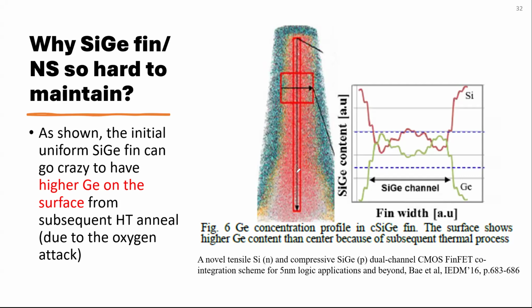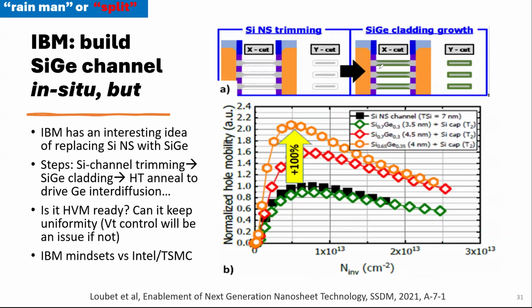But later in the process you get some high temperature anneals, there are tons of them, by the way, right? The ILD0, that's a steam anneal, oxidation. That's oxidation right there. Or the SDI anneal. SDI has a steam anneal as well, right? Then you will see that the edge has a higher germanium content. So if you have higher germanium content here, you're doomed. You lose control because DIT is very different. You definitely lose your VT control. So there you go. It's a beautiful idea, right? And then you'll be in deep trouble.